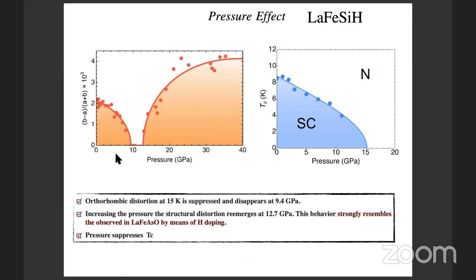So we studied the orthorhombic distortion in the presence of pressure. From this data, it's clear that the orthorhombic distortion disappears at around 9.4 GPa, but if we increase the pressure, it re-emerges around 12.7 gigapascal. Okay, so this feature is also similar to the iron-based superconductors. We also studied the pressure dependence of the superconducting transition Tc, and the Tc disappears around 15 GPa pressure.